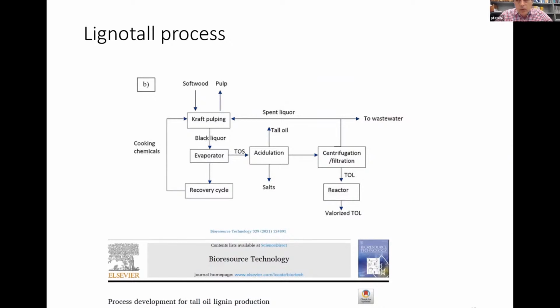So the other process that we worked recently with the help of CRIBE and another pulping company was Lignotall Process. So this is a brand new process that we developed at Lakehead University. So when you use softwood in a kraft process to produce pulp, you get tall oil. Following an acidulation system, you can extract the tall oil and sell it as a byproduct. But there's lignin there because the tall oil production is attached to black liquor evaporators. So they get the tall oil from the evaporator. So some lignin along with the black liquor comes to that.